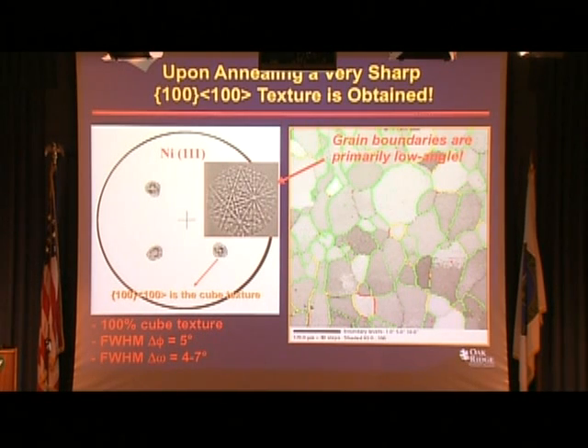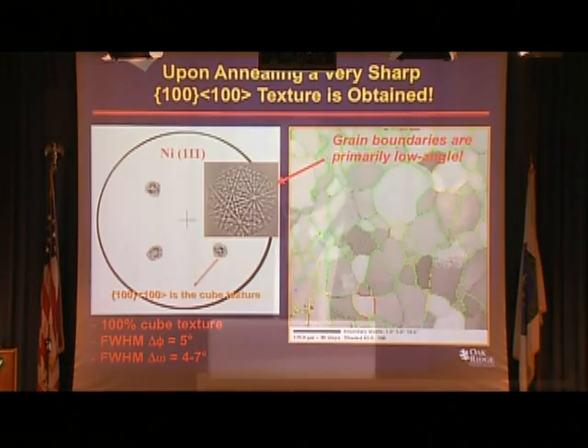Now, if you want to know what the grain structure is now, we can go back again to electron backscatter diffraction. Every pixel here is one diffraction pattern. So you can take 100,000 diffraction patterns and recreate the grain structure based purely on orientation. And when you do that, the green boundaries here are the low-angle boundaries, all less than 5 degrees. Now, if you remember a plot that I showed you at the beginning of my talk, if you're below 5 degrees, you can get lots of supercurrent transmission across the interface. So our goal now is to have the superconductor to have the same microstructure.